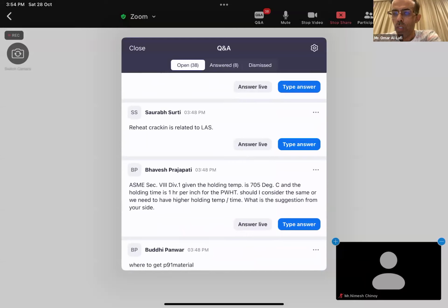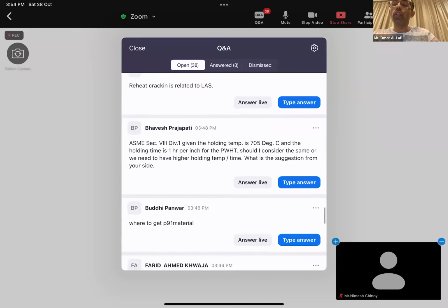To have higher holding temperature, what is the suggestion? So higher holding, as long as you are below the critical temperature, it is fine, but it can result in softening grain areas in the heat affected zone. So we should follow the specified holding time in ASME. I know some people who do the holding time 2 hours or more, or 5 hours at least, but we should follow the ASME standard.